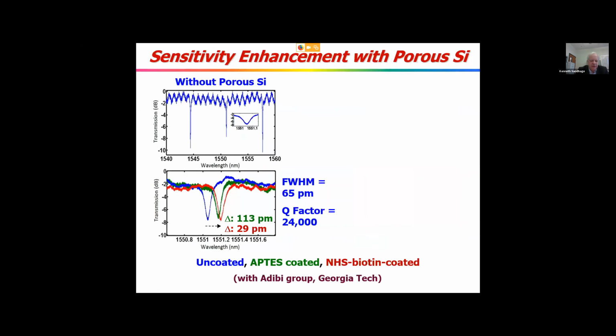So the Adibi group then measured the decline in transmission at particular wavelengths without the porous silicon layer on top. You can see that here, many decibels decline. If you zoom in on one of these, the 1551 nanometer peak, you can see the peak has a Q factor of about 24,000. They put aminopropyl triethoxysilane on that solid surface, shifted as you expect from the change in refractive index contrast a little bit, and then added NHS biotin, which covalently bonded to the APTES, and that shifted a little bit more.